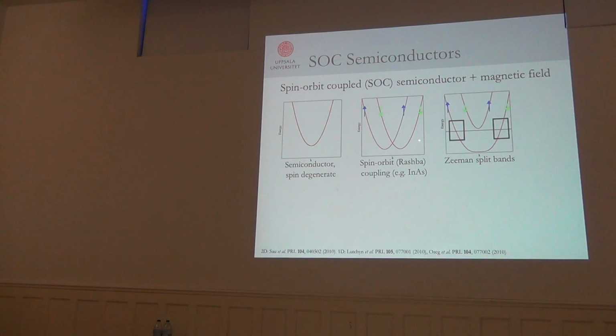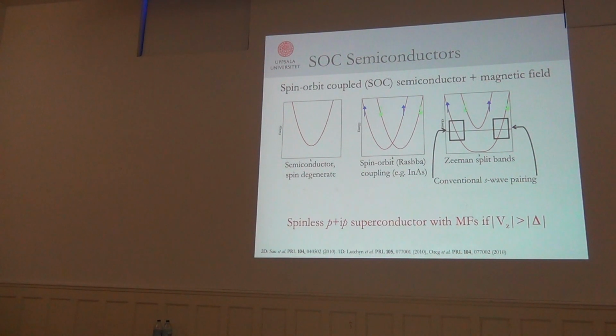And now all of a sudden, if your Fermi level is here, your system looks spinless. Yes, there is spin up here and spin down here, but there's no spin degeneracy left in your problem. We got rid of that pesky spin degeneracy that doesn't allow us to have the Majorana fermion. So now, if you pair electrons here and here, the good thing is you can pair with conventional S-wave pairing, because this one points up and this one points down. It's the pairing you need in S-wave spin singlet pairing. So you can take this spin-orbit coupled semiconductor with magnetic field and just add a conventional S-wave superconductor, and you will get something that looks like a spinless p plus ip.